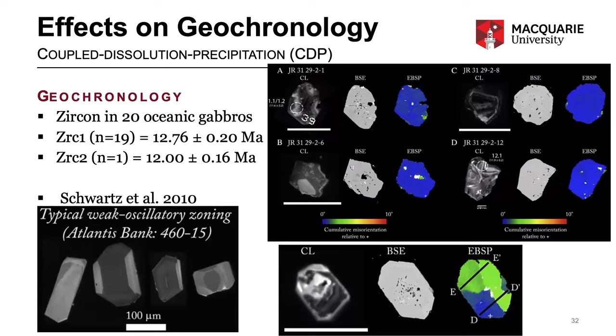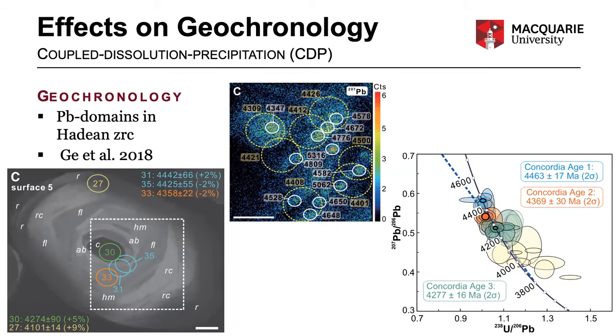19 in the interpretation. In Hadean zircons, where very detailed chemical mapping of lead-207 shows that it forms clusters and variation across the grain scale, integration of the data marked by the ellipses on the lead map show a vast spread of ages on the Concordia diagram that spread over a few hundred million years. I believe these complexities in detailed chemistry of the grain are formed through coupled dissolution precipitation and migration of the chemical components into different domains of the grain during that process.